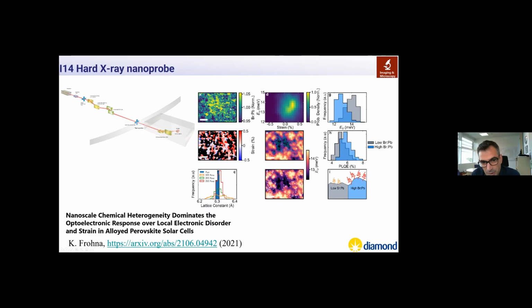So essentially they try to map the defects, the chemical inhomogeneities, the strain, and the composition, and correlate that with experiments they do with other techniques, so photoluminescence and also electron microscopy in this case, trying to get a full picture of why this defect drastically reduces the electronic response of this material and how the electronic disorder is introduced in this system. So this is an example of where correlative microscopy is very, very useful.